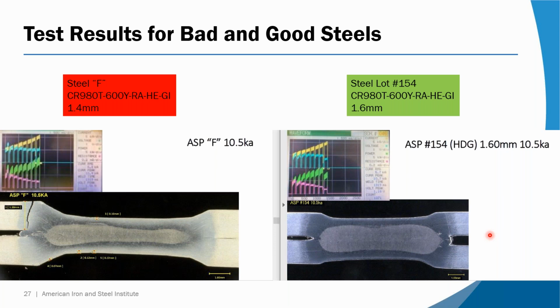10.5, okay, more of the same. You just have more indentation here. You see how this is well into the heat affected zone, and that same approximate temperature regime and indentation and everything is not producing the cracks in this material.